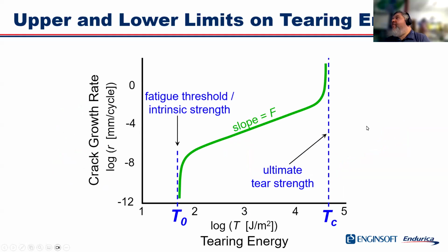Here's an example of rubber's fatigue crack growth rate curve, and there's two or three features on here I want to point out. Like I say, if the energy input to the crack is sufficiently large, T sub C, that's the critical tearing energy, then at that point the crack is just going to grow spontaneously, right?